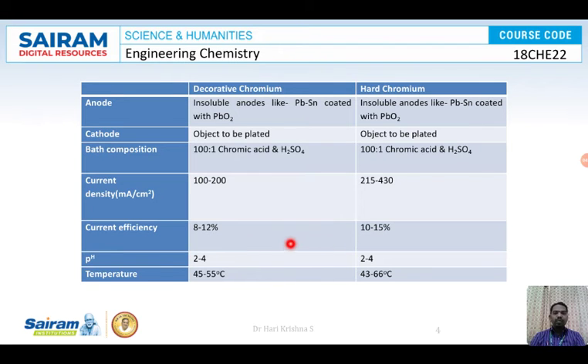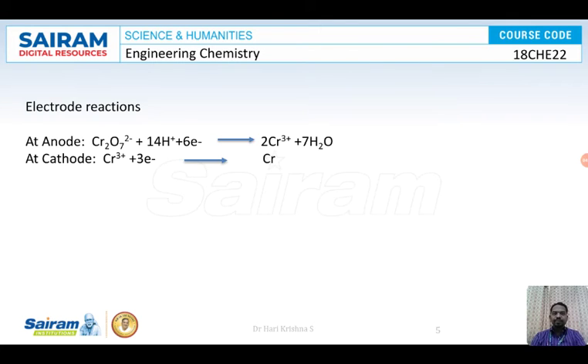For pH, for both it is the same. Why? Because the electrolyte, or the bath, is the same, right? The electrolyte itself is called the plating bath solution. So what is the electrolyte? It is chromic acid and sulfuric acid. It is an acid, right? So the composition is the same, 100 to 1. So the pH remains the same, it is 2 to 4. Temperature is 45 to 55 degrees Celsius in case of decorative chromium plating. In case of hard chromium plating, it is 43 to 66 degrees Celsius.